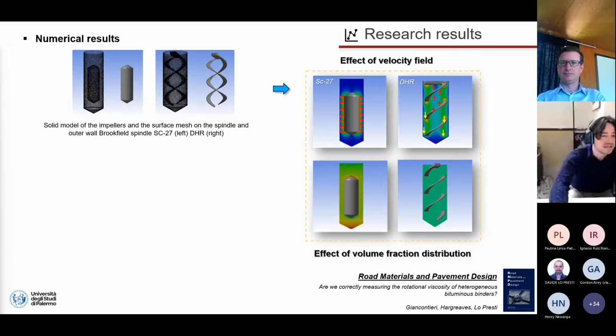The numerical campaign indeed helped to identify that the SC27, due to its geometry, creates a low velocity field at the top and the bottom of the tube, as you can see from the simulation, while all the stresses are distributed around the vertical wall of the spindle. The DHR instead allows a better distribution of the velocity flow field, thanks to the axial pumping, where the inner blades push the fluid upwards, while the outer push the fluid downwards, allowing a continuous recirculation of the fluid flow.